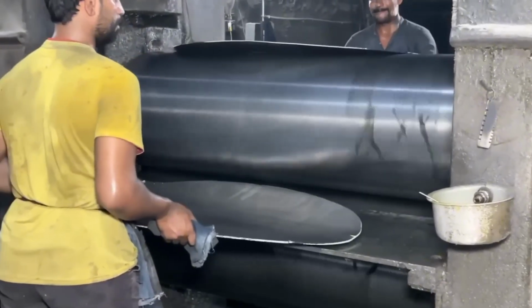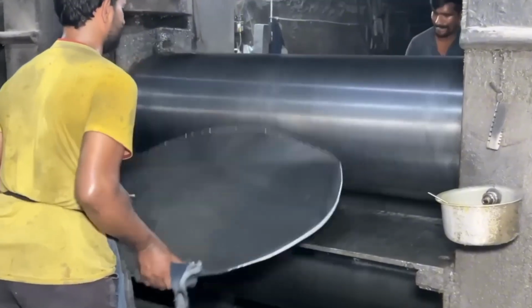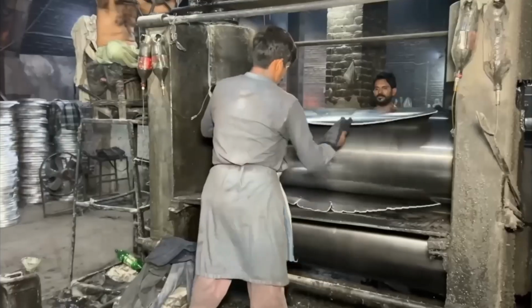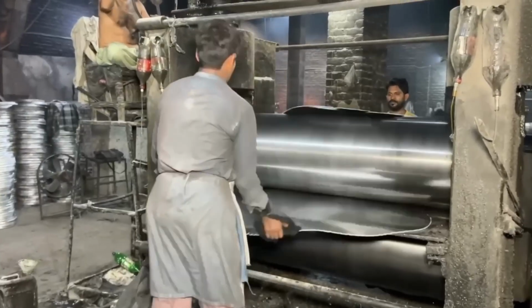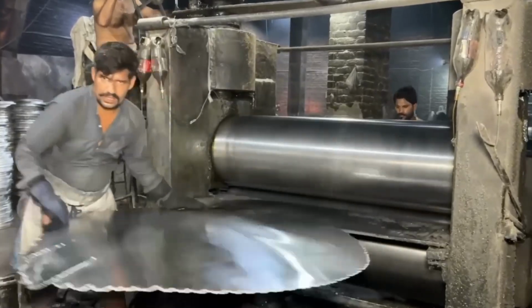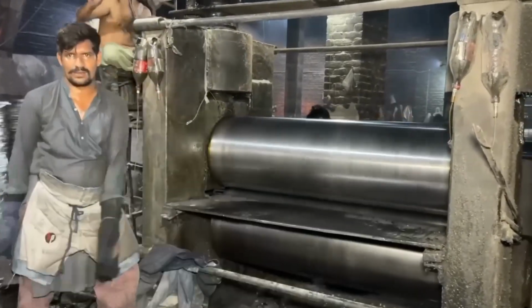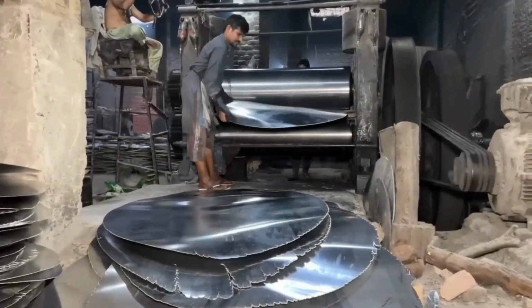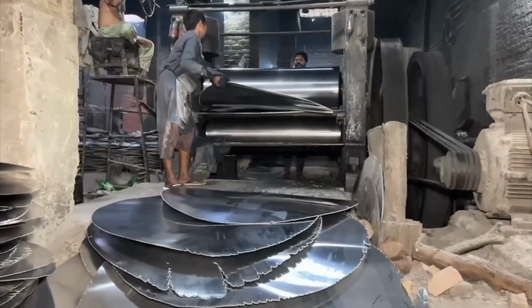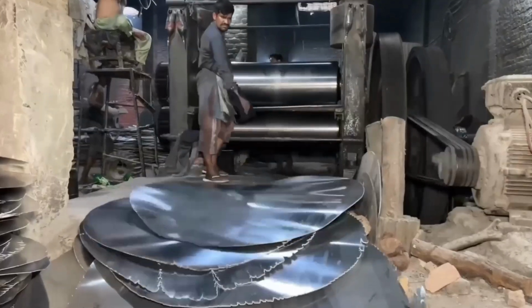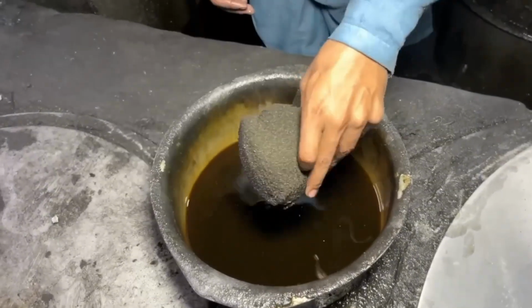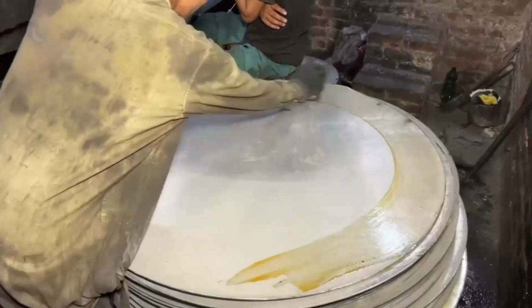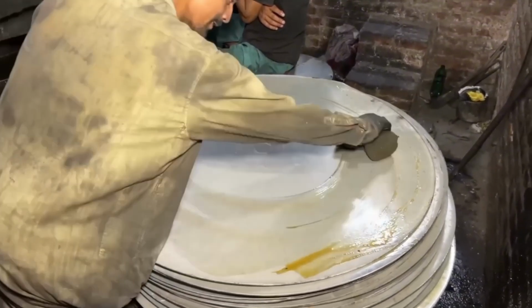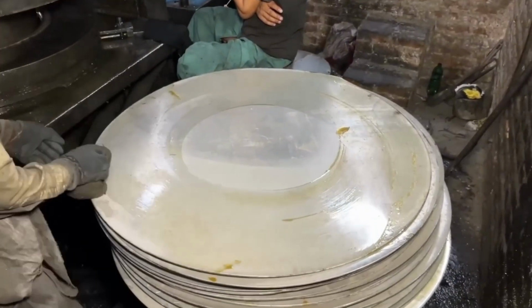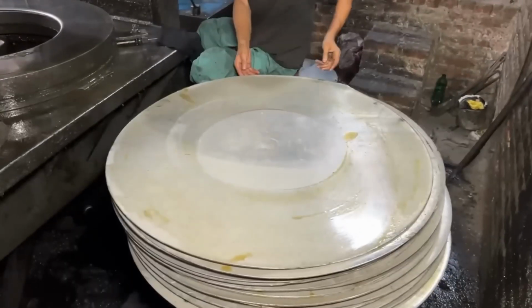Once thinned, the large aluminum sheets are cut into rough circular blanks. Disc preforms. These stacks of disc blanks return to the furnace once more for annealing. After the rolling pressure, the metal hardens. Reheating restores ductility. Before pressing, each blank is coated with a heat-resistant lubricant oil. This layer prevents the aluminum from sticking to the die or tearing under immense pressure.